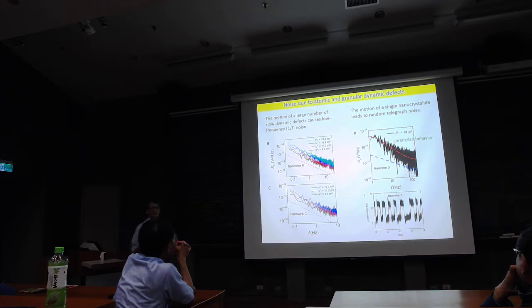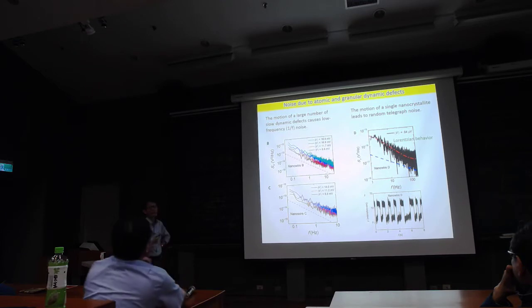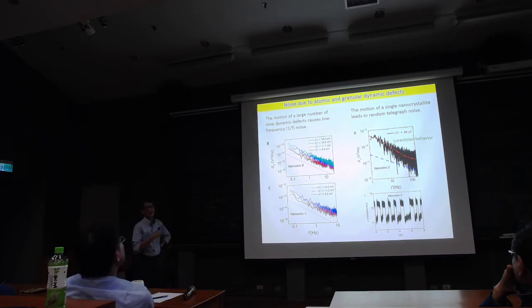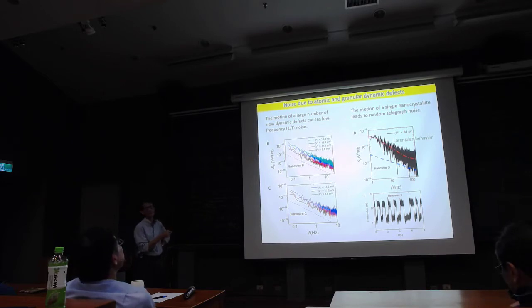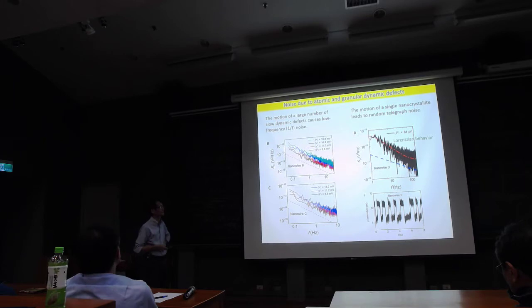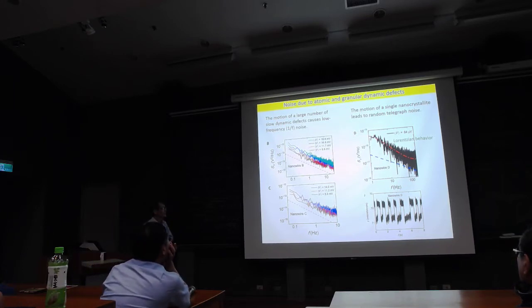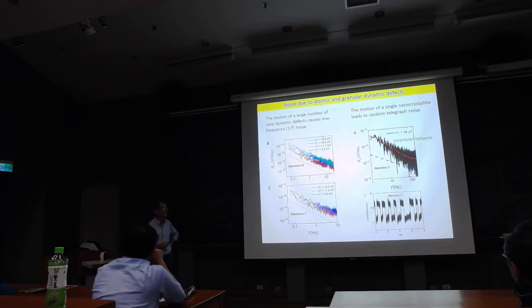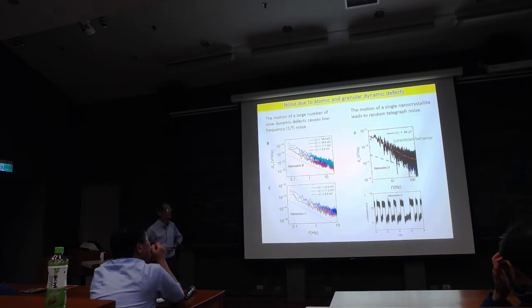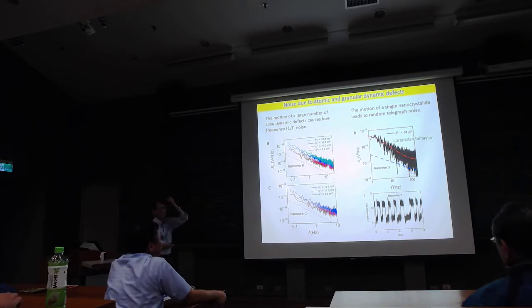Okay, this is non-Kondo physics. In real nano devices, some atoms may move very slowly, and this gives us noise. This is so-called 1/f noise. This is a very slowly moving defect or two-level system. And if you have not just a single atom but a group of atoms, for example, a nanoscale crystallite, the chance for it to move back and forth is very slow. But still, that can happen. So if that happens, and if you can catch the signal, it will give you so-called random telegraph noise. And nowadays, when you go to smaller and smaller devices, this could be very, very important.